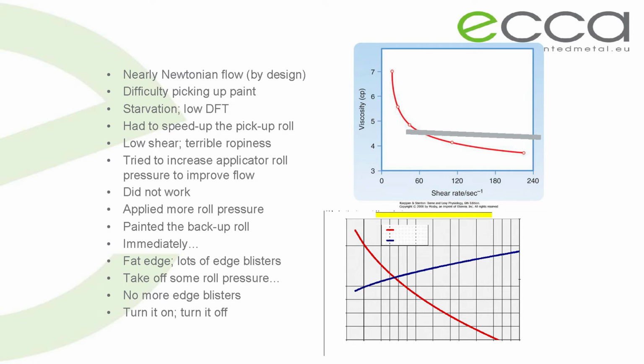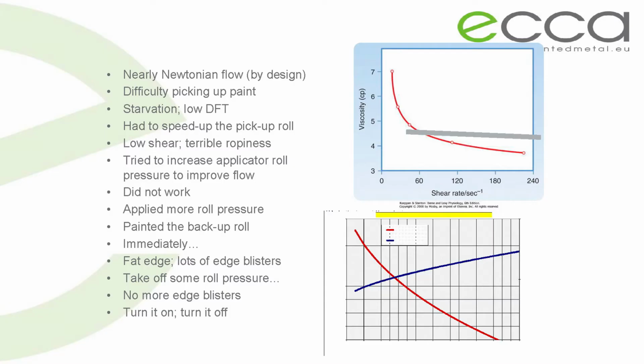So what's the first thing you do? You increase the applicator roll speed. Well, actually what we saw first was starvation, so we knew we were about as slow as we could go. So we had to increase the pickup roll speed. Now all of a sudden, and I mean immediately, we saw a ropey flow. By the way, our competition was on the coater upstairs, and their flow was just perfect. So it was very disappointing.